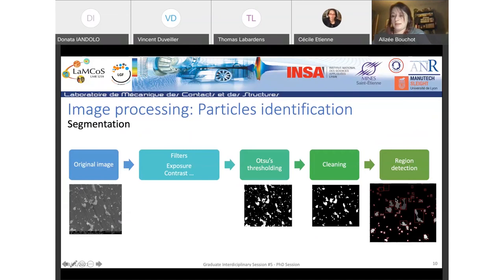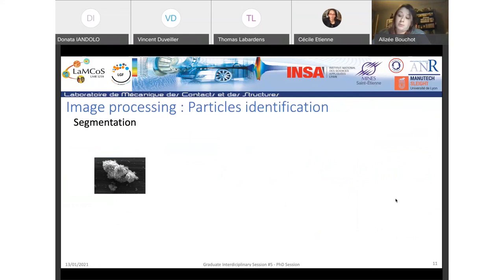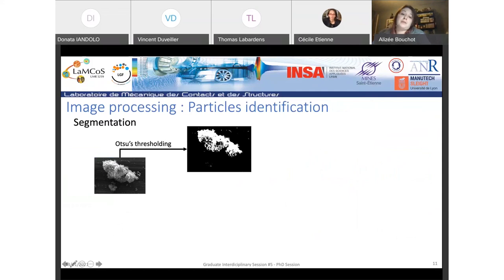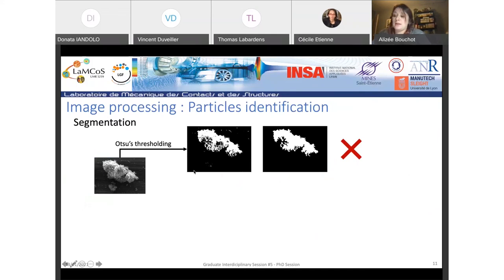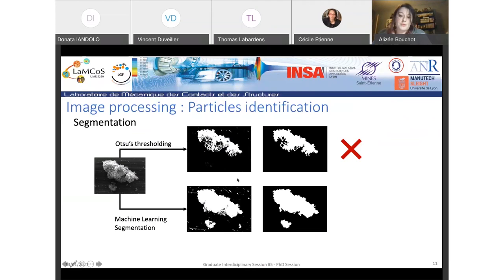It may happen that the texture of particles or agglomerates does not allow segmentation by thresholding, as on this agglomerate here. If I do an Otsu thresholding, that is the result. So the shadowy area will be interpreted by the algorithm as a hole, and we will lose information. To overcome this, another code has been developed. It uses a machine learning algorithm and allows better segmentation in the case of complex texture. You have the result here. So we lose less information in this case.